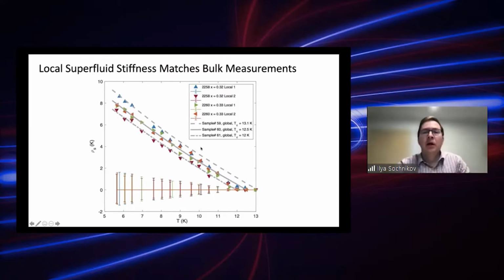They all fall within these two dashed lines, or three gray lines, that are taken from the bulk measurements, and essentially within the error bars of our experiment, which are shown here, we pretty much confirmed the linear dependence of the superfluid stiffness, in basically an agreement with the bulk measurements.